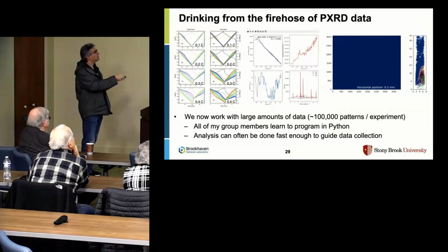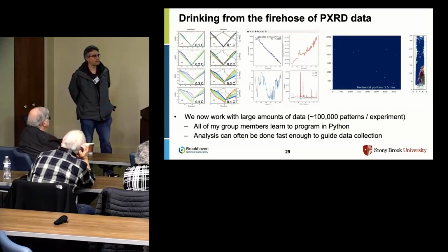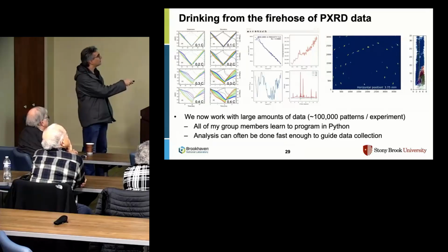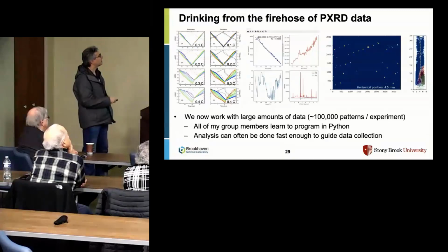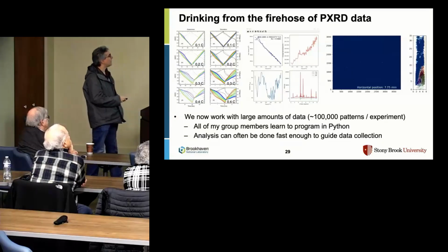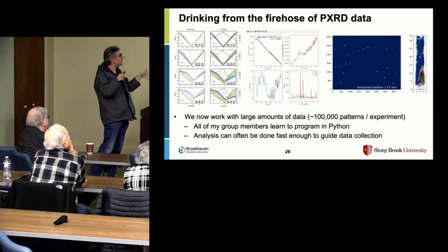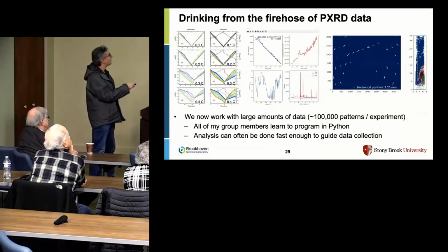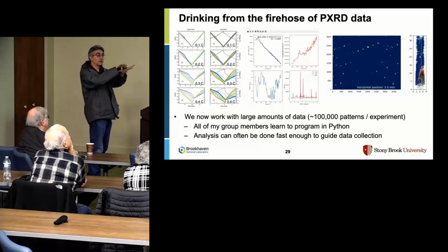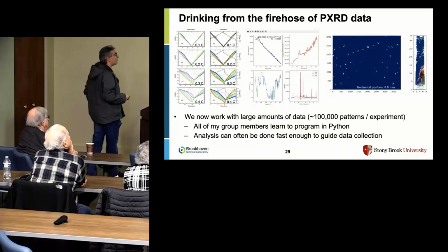The stuff on the right is us using a powder diffractometer to do single crystal diffraction work. Here's a 3 centimeter boule from a floating zone crystal, powder at the bottom, the single crystals on the top. What was really curious here is that this is sort of a composite image for everything on the line. You can see it moving from left to right. On the left side of the crystal, the peaks are very spread out, indicating a lot of mosaic imperfection. On the right side, they're very spread out, but in the middle, they tighten up, which I think is telling us something about the influence of the curvature of the solid-liquid interface on the single crystal growth.